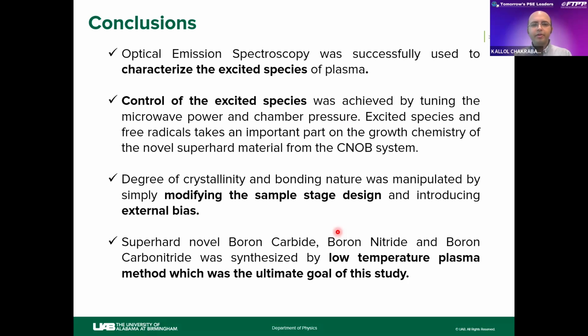Optical emission spectroscopy was successfully used to characterize the excited species of the plasma, and control of the excited species was achieved by tuning the microwave power and chamber pressure. Excited species and free radicals take an important part in the growth chemistry, and the novel superhard material was made from the CNOB system.